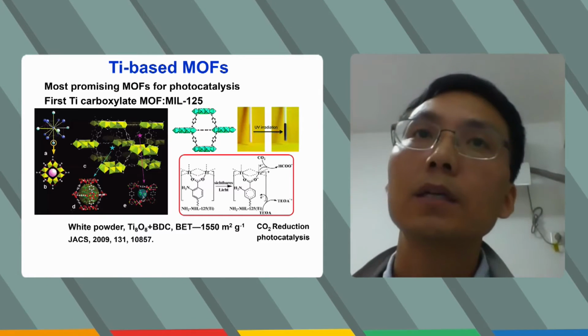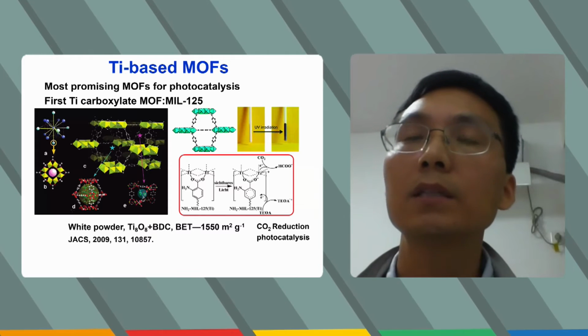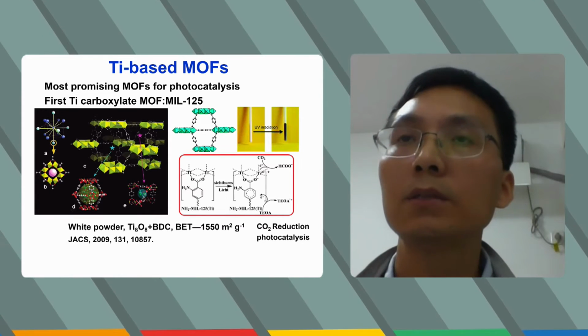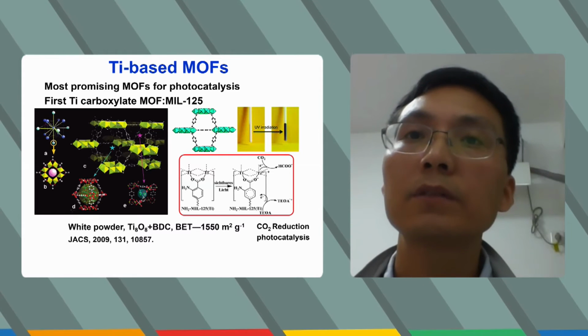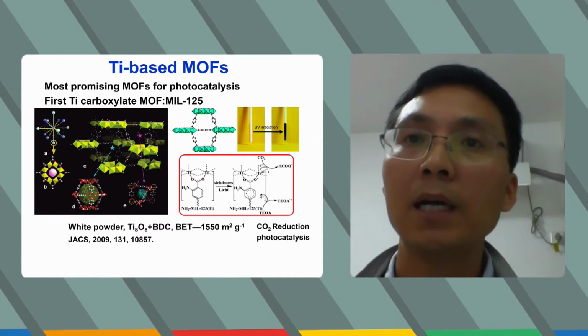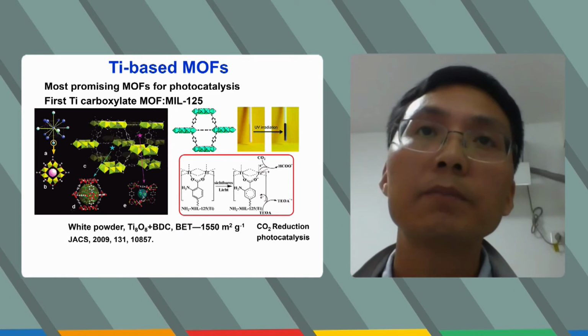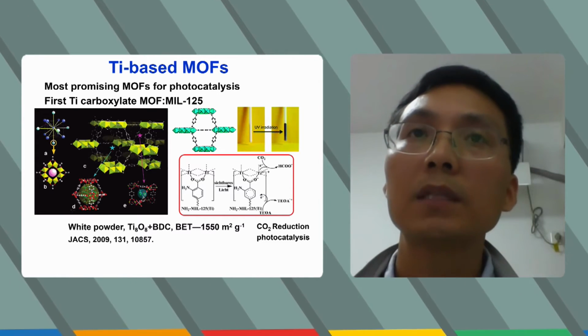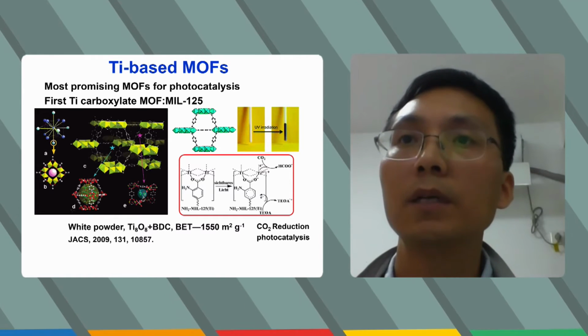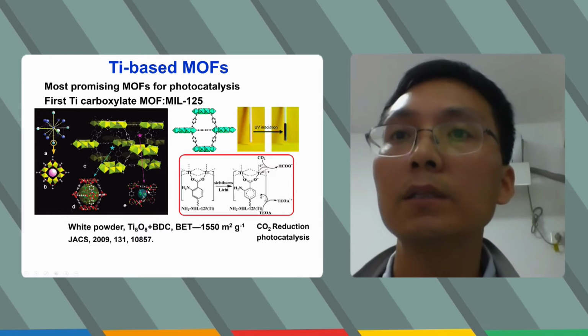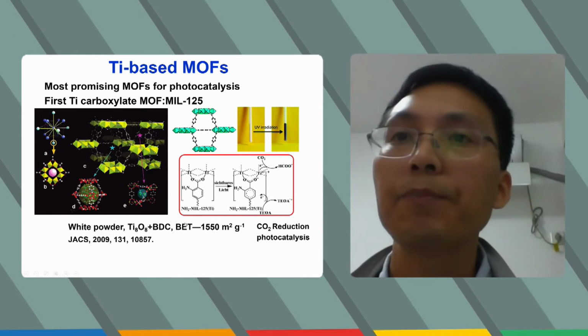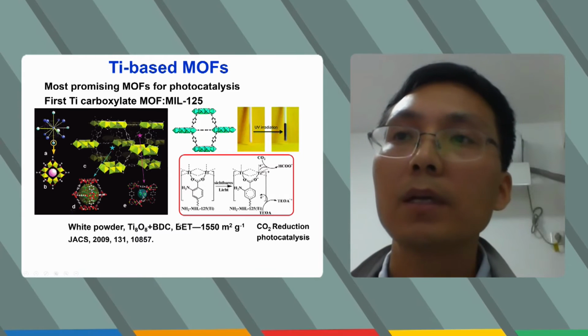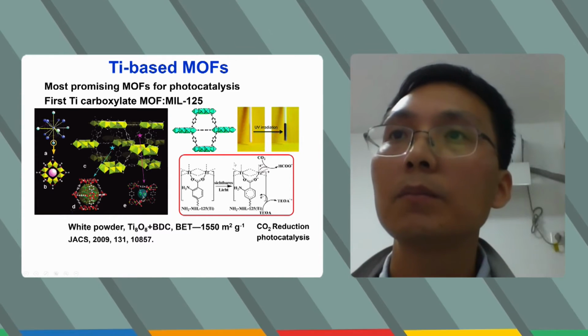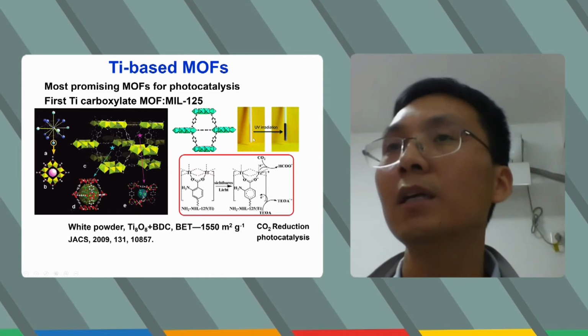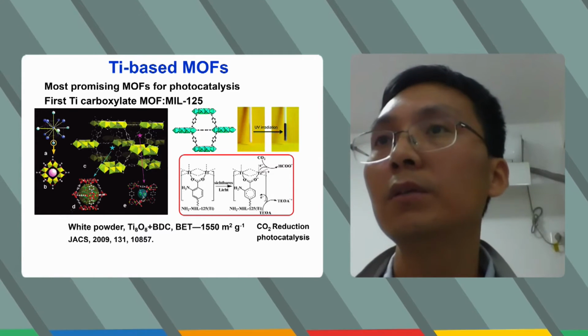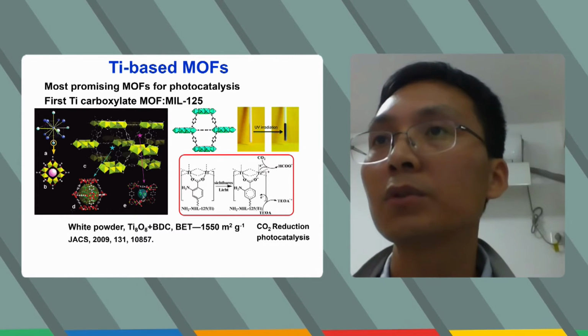The first and the most studied titanium MOF is MIL-125. It was first published in 2009 by Férey. This is the first titanium-based carboxylate MOF. This MOF has a very large BET surface area, but as we all know, the color of this MOF is white, so it can only utilize the UV region. It cannot absorb visible light.